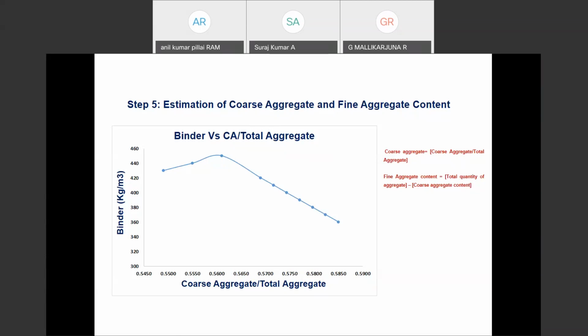There the binder content we had varied from 360, 420 and 450, and coarse aggregate to total aggregate we have taken the values from 0.54 to 0.59, so that based on binder you can select the aggregate, means coarse aggregate to total aggregate ratio. Once you know the coarse aggregate to total aggregate ratio, automatically you can get the